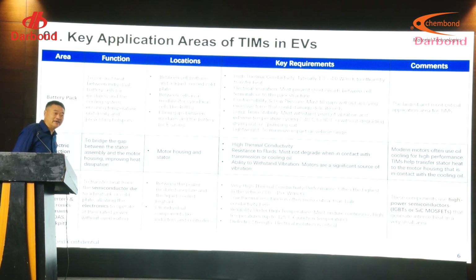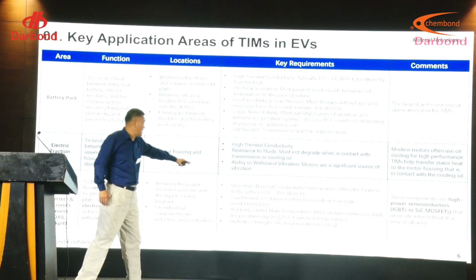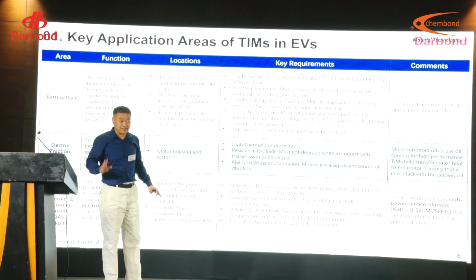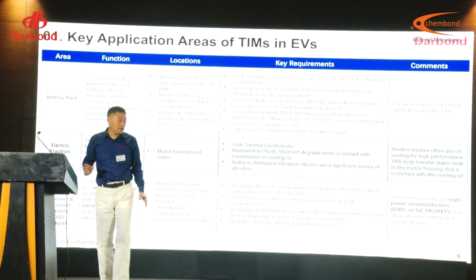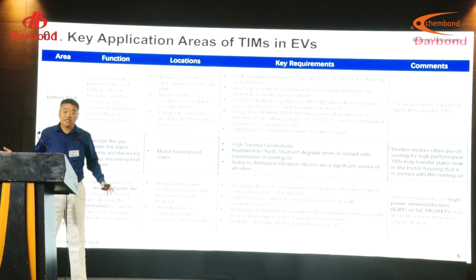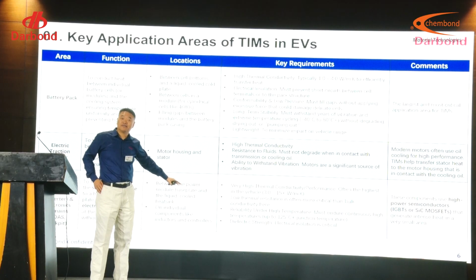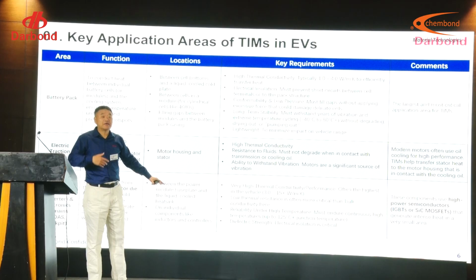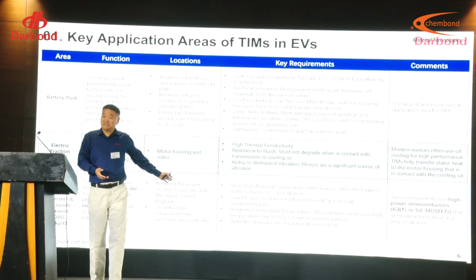This obviously gives requirements for this part. But most importantly, actually, is the powertrain. We call it power electronics, and there is also what we call the automobile electronic domain. No matter what, it's basically to transfer heat from the semiconductor die itself, or from the module itself, to the cold plate. This is a very high-demand area for thermal transfer in EVs, maybe the highest. Usually we need a thermal conductivity between 3 to 15 watts per meter-K. And then you need the lowest thermal resistance at the semiconductor die, and of course you need high reliability.